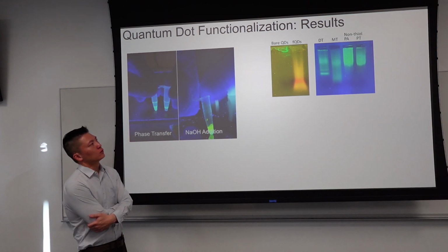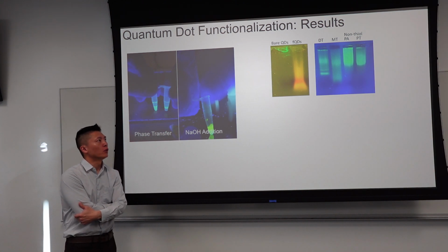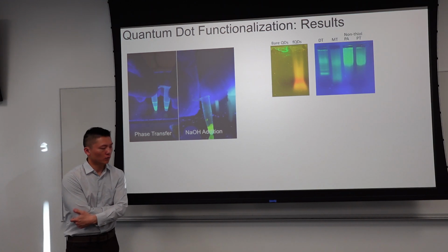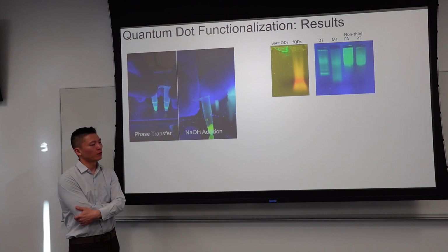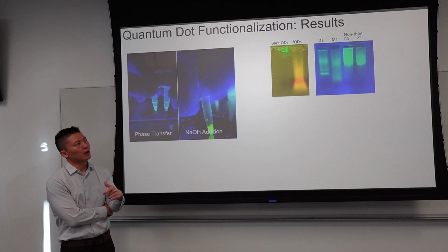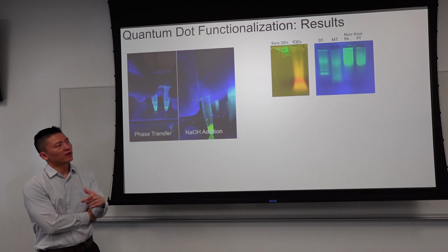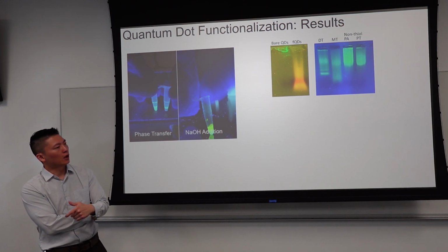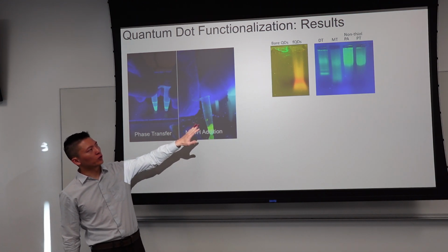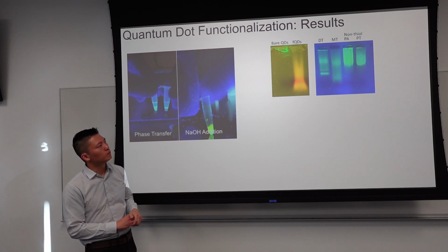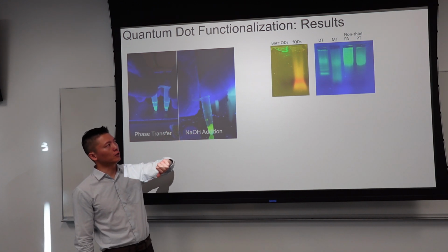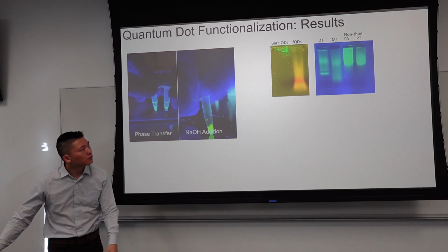I would also work with dithiol instead of monothiol. Romani was using monothiol in her work, and I'm now taking over and considering dithiol. Dithiol just has two sulfur groups as the anchoring head group to the surface of the nanoparticle. So we want to switch to dithiol because this is going to be a stronger ligand attachment, so we expect more stable assemblies. Anyways, it does show that a band was made there. Very different results here, so this was kind of promising for us. And I do compare these to non-thiolated oligos, poly A and poly T strands.